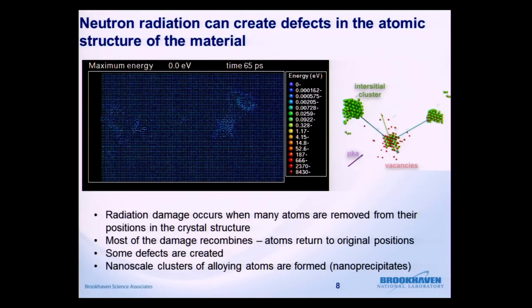So the atoms are returning to their equilibrium positions. And now at 100 picoseconds, many of the atoms have returned to their equilibrium positions, but defects have been created. So some defects remain in the material. Not all of the atoms are able to return to their initial positions. And in steel, this causes the clustering of alloying elements. So you get clusters of the alloying elements in the steel, and these are known as nanoprecipitates.